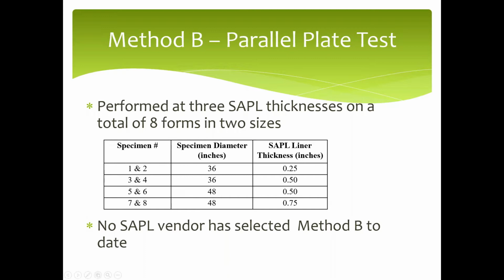This is good. Okay, so method B, I'm not going to go into a lot of detail about this, but we do have a whole host of pipes again. We have 8 samples at this point, and these are the forms, i.e. the sono tubes, in 2 different sizes, 36 and 48, and we have 3 different thicknesses. We have 0.25, 0.5, and 0.75. Again, we have 2 of each of these that we're going to test.